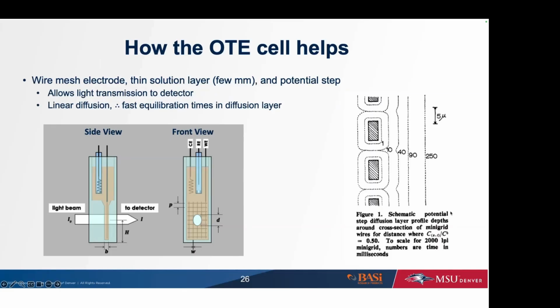And what this is showing us is that as you get a smaller spacing and smaller wires, you can increase the kinetics of diffusion towards the surface, and you create a more linear diffusion regime, which enables fast equilibration times with the diffusion layer and gets you to a more full transformation from the initial species and the redox generated species quicker. And that enables us to characterize faster processes in solution and see faster transformations.